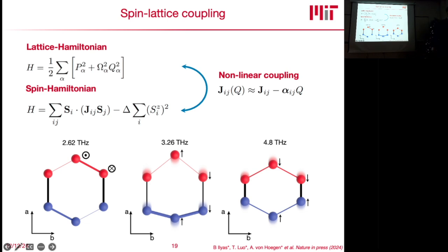Yes? And you said to start with, all of those phonons are only Raman active? Yes, they're all Raman active. Exactly. These modes are all in plane, right? Your application of magnetic field is perpendicular to the AB plane, right? Yes. So they are more sensitive to in-plane activities? Yes. So the different colors here, sorry, I haven't pointed that out. Thanks for reminding me. These colors mean spin up and spin down. The spins on these atoms are all pointing out of plane. That's something I forgot to mention. So at least to my naive understanding, it would make sense that the magnetization would also point out of plane if you start modifying these spins and exchange interactions.